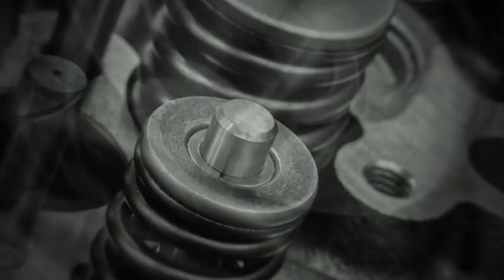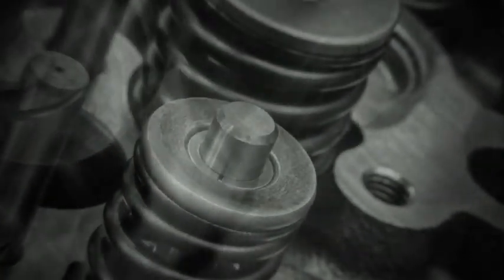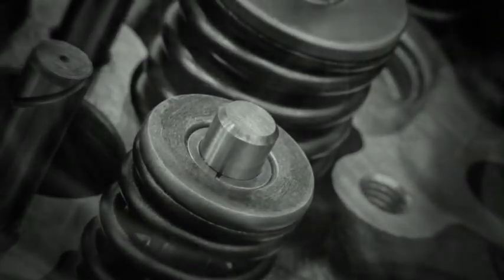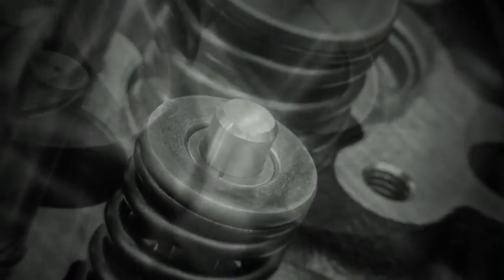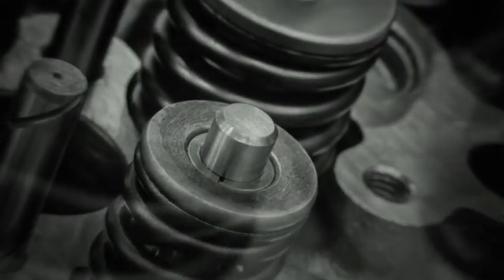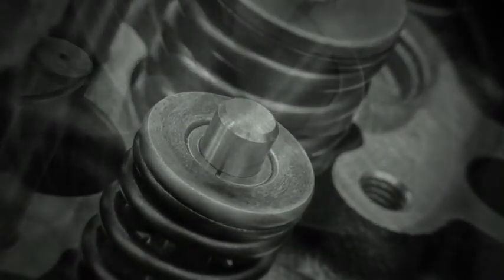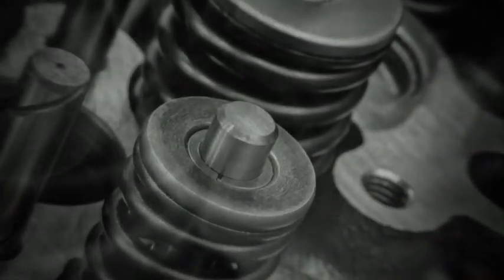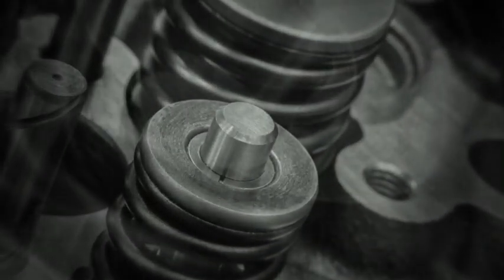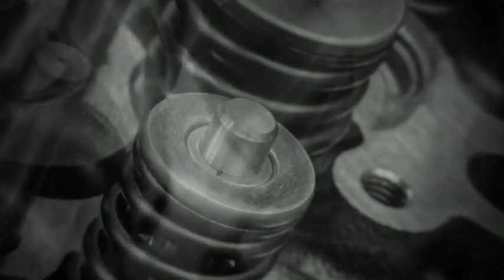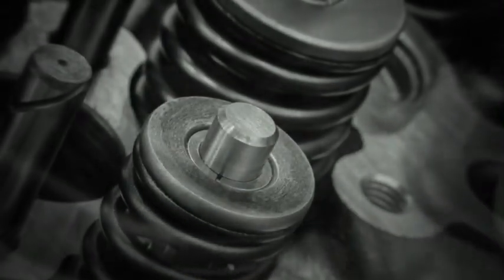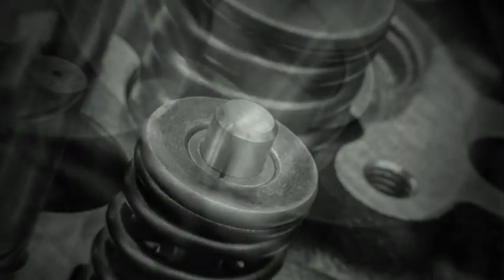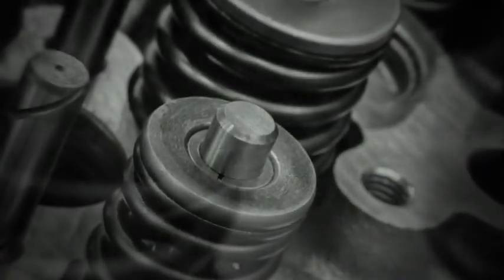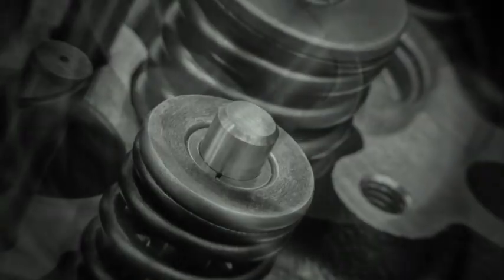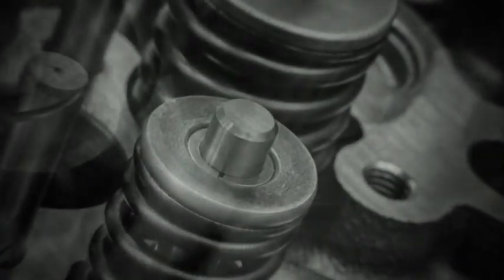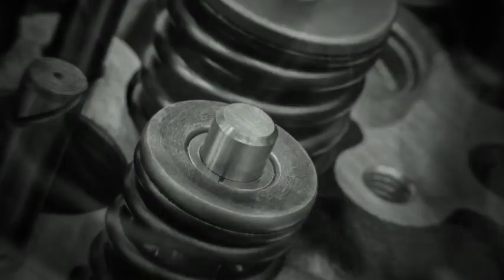Hydrogen embrittlement produces delayed fracture, with little plastic deformation. It is particularly dangerous because the spring can break while sitting under assembly load rather than during a visible overload event. Diagnosis requires the full system. Replacing a broken spring with an identical part may lead to another failure if the seat is misaligned, the damper is seized, the environment is corrosive, or the mechanism reaches an unintended stop.